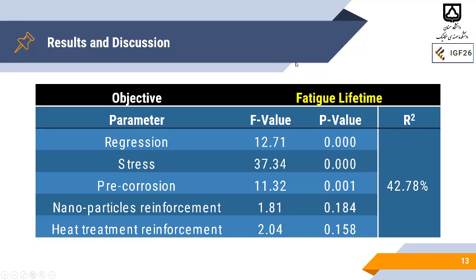For the regression analysis, we used fatigue lifetime in a normal scale. So you can see the parameters: F value, P value, and R2, the coefficient of determination. You can see the coefficient of determination is so low, it is not near 100%. So it means that the regression modeling is not good and not proper. For the regression, we have a p-value less than 0.05, so it means that the regression was meaningful. And here stress and pre-corrosion are the effective parameters.